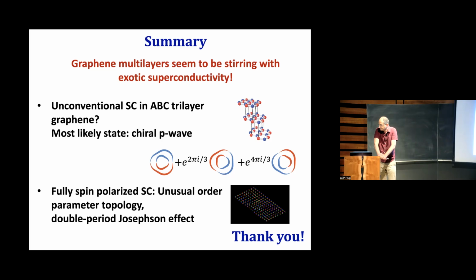Do you understand that resistivity that you showed? At the following level. I would say this is the mechanism, and if for some reason electron-phonon coupling is weak, then these are very clean and low density systems. So even if electron scattering is very strong, it won't show up in the resistivity. There's no umklapp scattering. But your resistivity was more or less flat in temperature. That's exactly what you would expect. Yes, you expect flat resistance. But that only usually comes from impurity. And you said there are no impurities. Yeah, so the resistance might just come from the boundary of the system. From the boundary. That we really don't know.